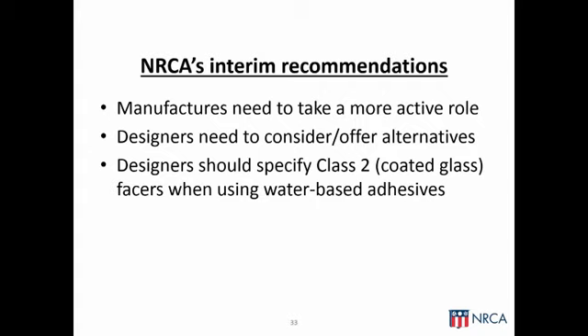Designers should consider specifying Class 2, in other words, glass-coated facers, when using water-based adhesives. And that is something coming out of the joint NRCA-MRCA testing on water-based adhesives. We're seeing those peel strength issues with paper-faced ISO. In other words, the water in the water-based adhesive is having an impact on the facer sheet. The way to address that is to not use a paper-faced facer.